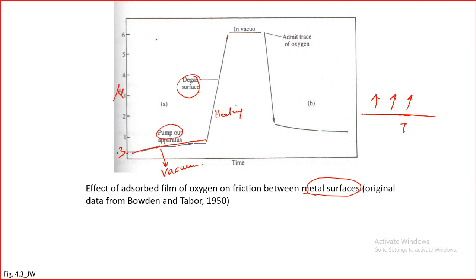which is almost like cold welding, what is known as cold welding. This term is also used in junction growth theory. So very, very high coefficient of friction. Then they introduced a trace of oxygen, just a little bit of oxygen, and the coefficient of friction again went down to a very low value here and continued like this. Again, if you remove the vacuum, the coefficient of friction will come down again. This was done quite early on, in the 1950s, and it was proved that vacuum increases coefficient of friction, and the reason is the removal of the contaminants from the surface.